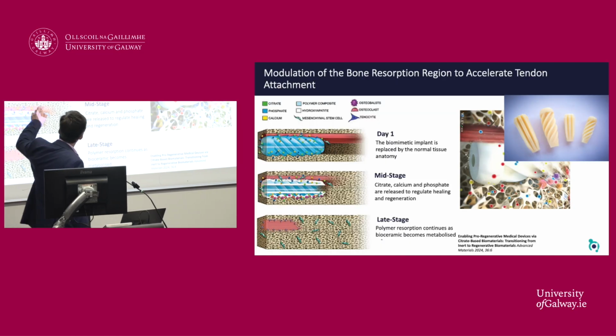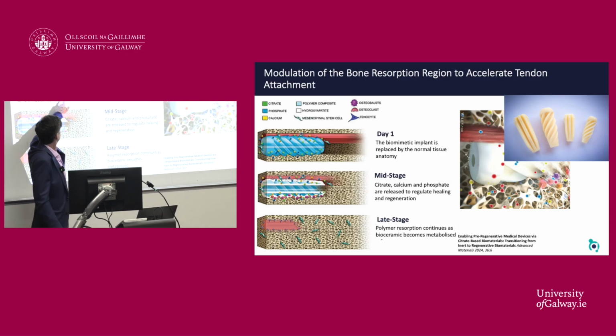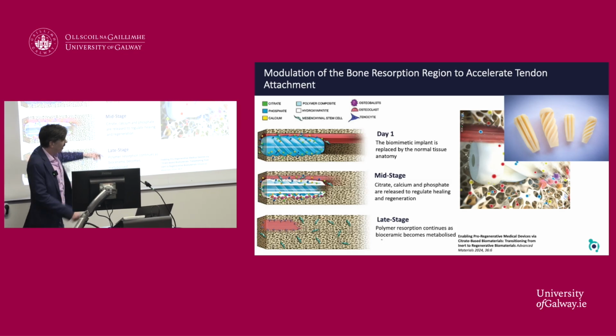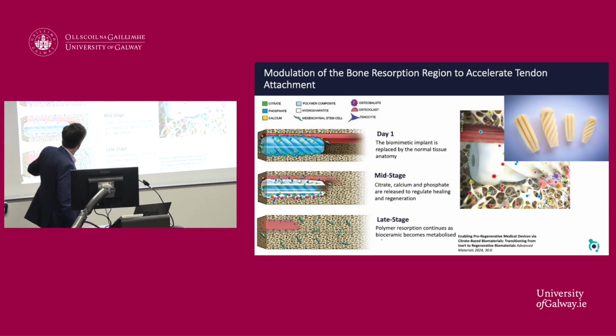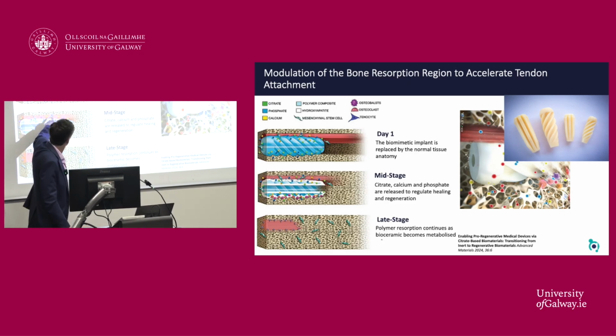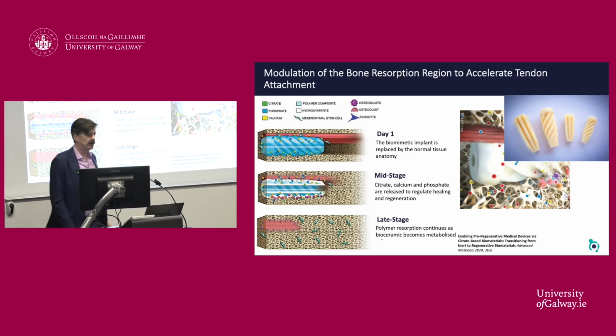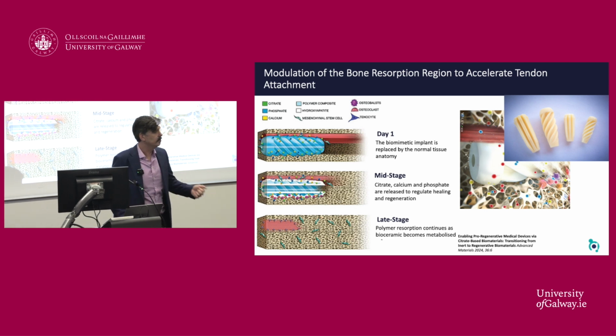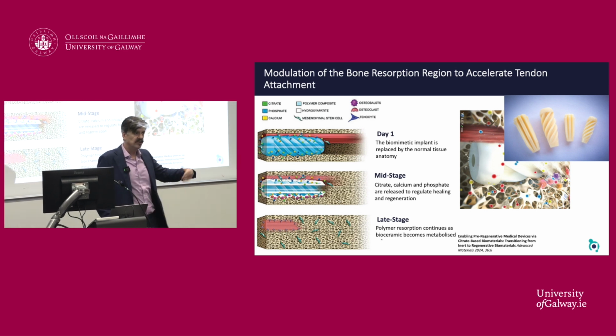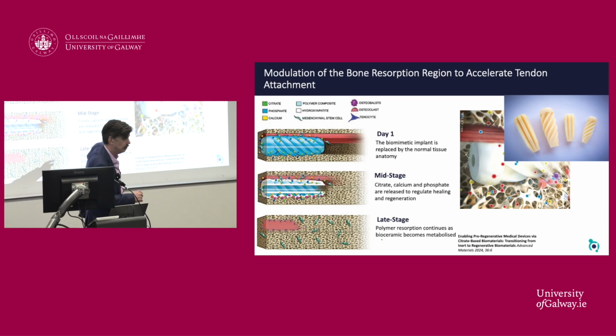Here you can see that. Day one, surgeon creates a void. The tendon is placed in there, and the Citralock is the tendon anchor. Over the course of about 12 to 24 months, the material will start to break down. So the citrate and the calcium and phosphate ions from the ceramic will start to leach into the surrounding tissue, into the void.